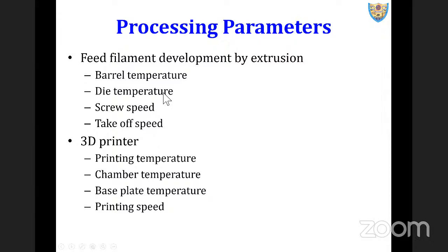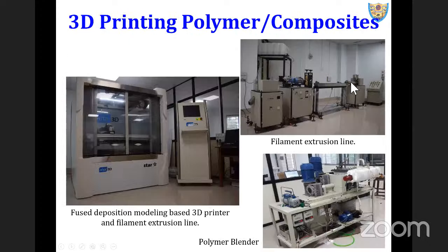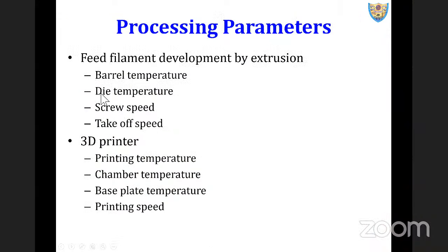And when we do that, we need to find out suitable parameters for blending, for filament extrusion, as well as for printing. In this filament extrusion, we have barrel temperature, wherein we have a barrel here. There are 4 heating zones. This is procured from Asabi, Thane, Maharashtra. Then we have die temperature, screw speed, and takeoff speed. These define the filament diameter, whichever diameter you want. Barrel temperature and die temperature decide the temperature profile from the feed section to the die section, and that again we decide based on Tg, melting, and degradation temperature of the polymer.